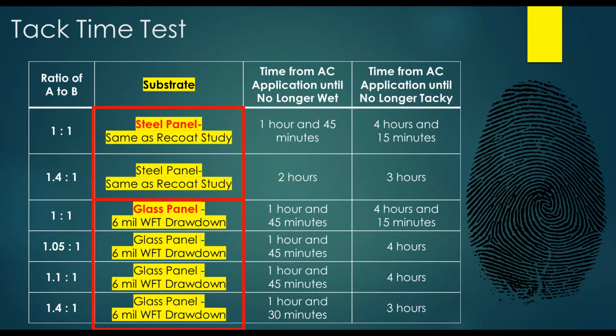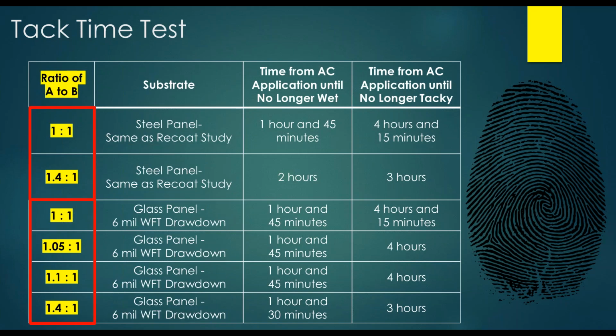We looked at two variables. We looked at the effect of the substrate, so we looked at both steel panels and glass panels. Similarly, we looked at different mix ratios. This was in the range of the control samples, which were a 1:1, and then we went as high as 1.4 hardener to 1 part of the resin component.